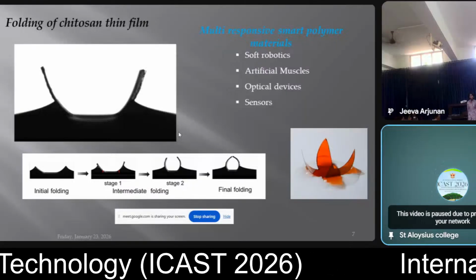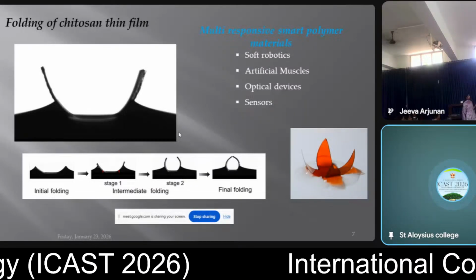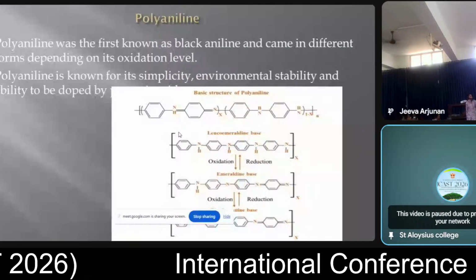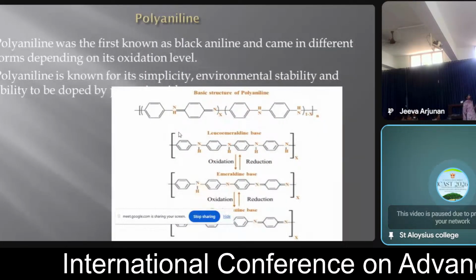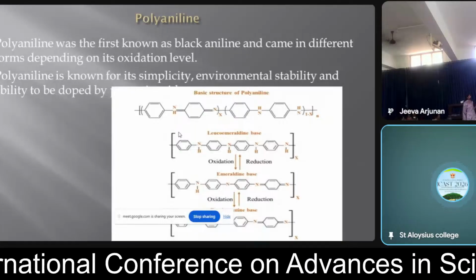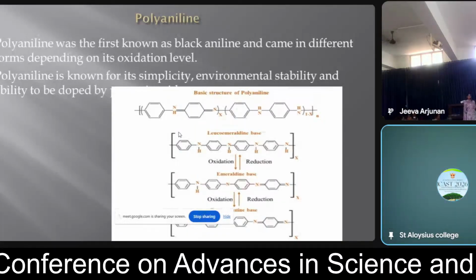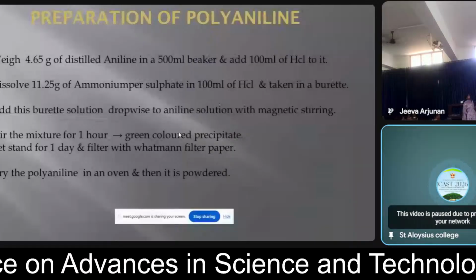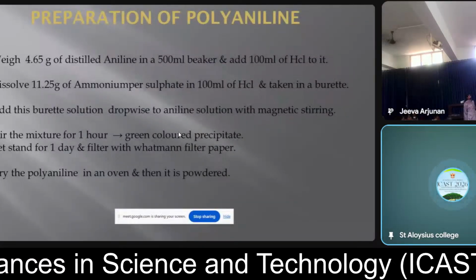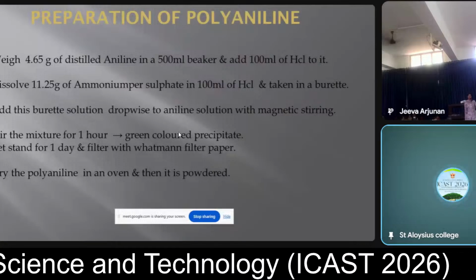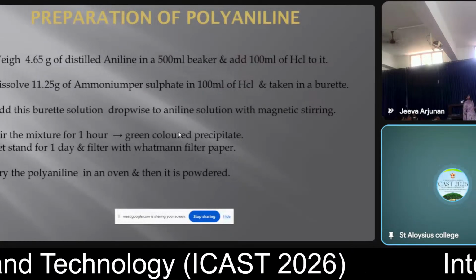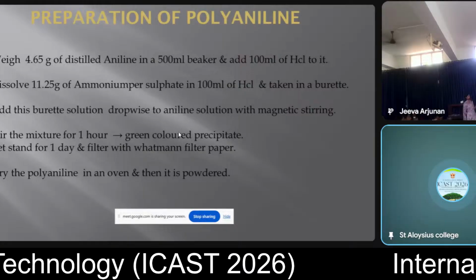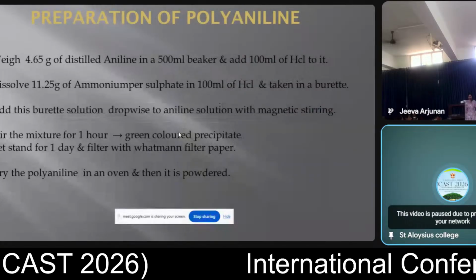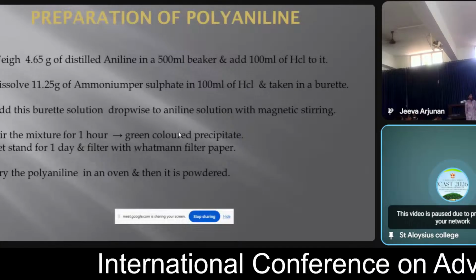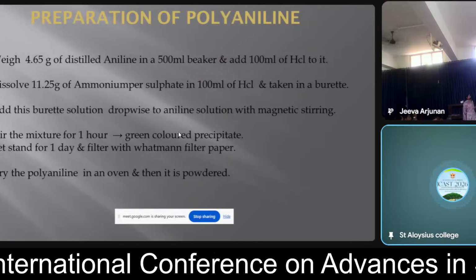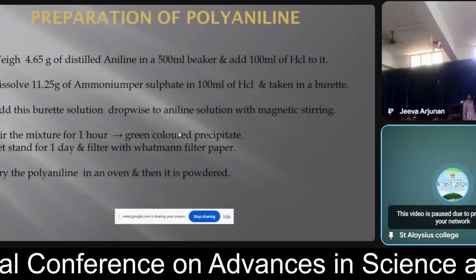The next compound we use is polyaniline. Polyaniline is a first-generation aniline-based polymer. It can exist in different forms depending on doping and oxidation level, and it has high environmental stability and simplicity. For the preparation of polyaniline, we weigh a definite amount of distilled aniline in a 500 ml beaker and add 100 ml of HCl. On the other side, we dissolve ammonium persulfate in 100 ml HCl and add it dropwise into the aniline solution. We stir the mixture for 1 hour and get a green-colored precipitate. We let it stand for 1 day, then filter, dry, and powder the polyaniline.